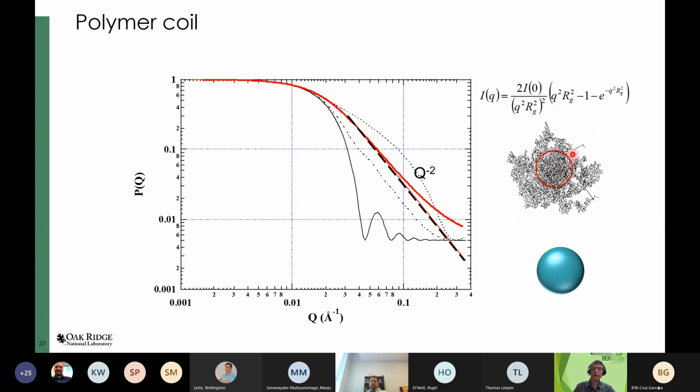So again, I used the same overall RG as for the sphere. This whole thing overall is more extended, so you have things farther out, but it's less densely populated. So these two objects again have the same overall size parameter, even though this one is overall wider, but it's just more distributed. And the scattering curves again are very different. This is the sphere, the black one, and this red one here is the coil. So you can certainly distinguish compact objects from diffuse random coil objects quite easily in scattering.